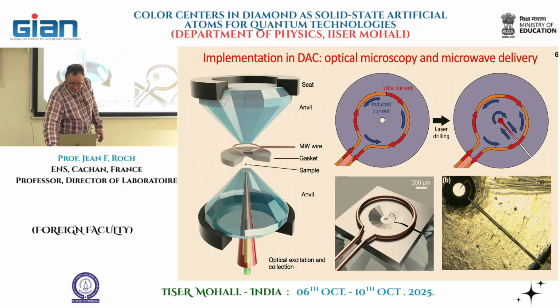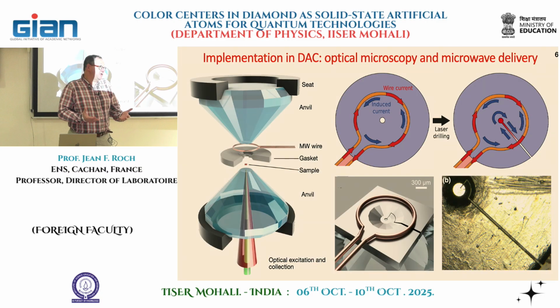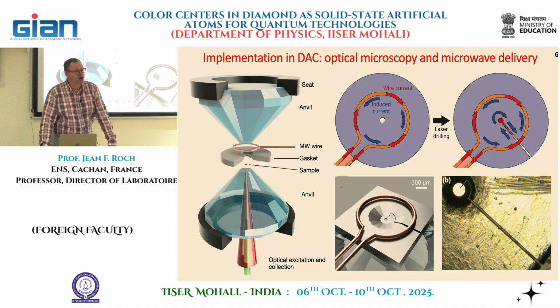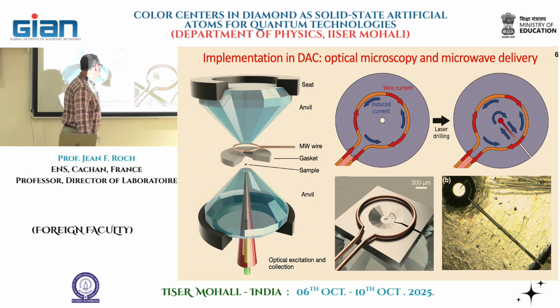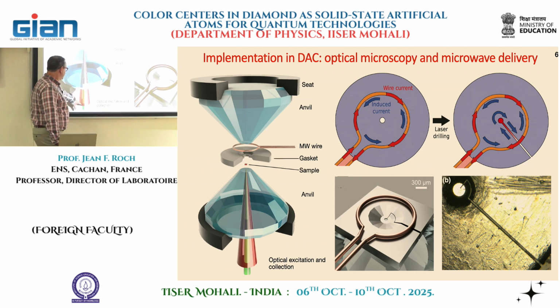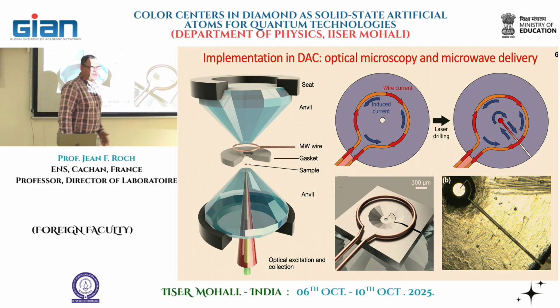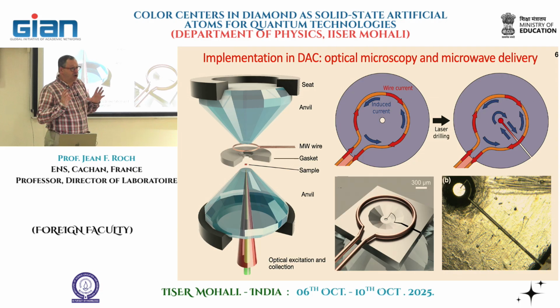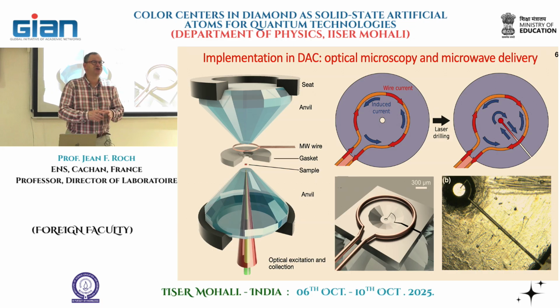So we do that, and now what you simply have to do is basically to implement all the tools I discussed with the constraint of a diamond anvil cell. So basically the idea is very simple. Diamond is transparent, so we can excite the NV layers through one anvil and collect the light emitted by the NV layer through the anvil again by the same microscope objective here. We have to apply the microwave excitation. And for that, we wanted from the very beginning to avoid anything inside the cell, close to the sample, and to have a microwave excitation as homogeneous as possible.